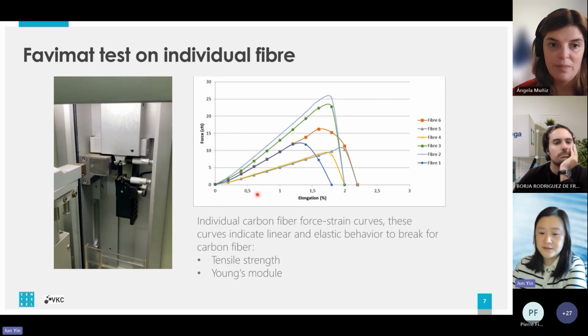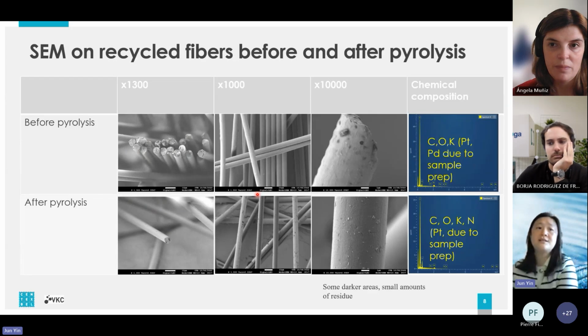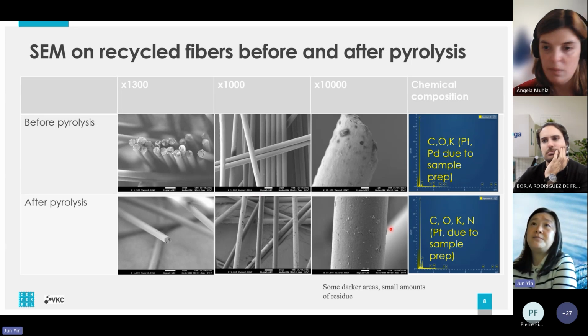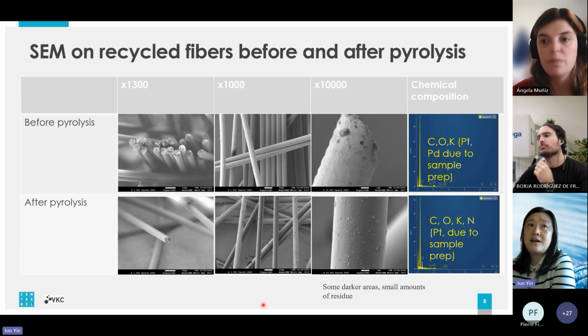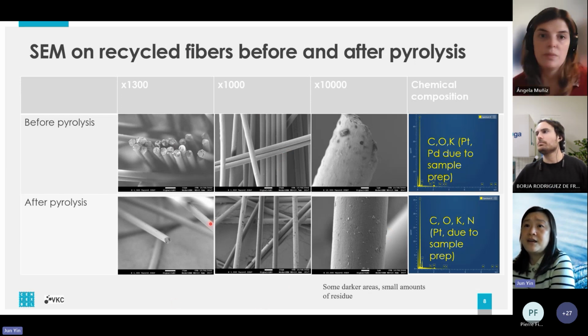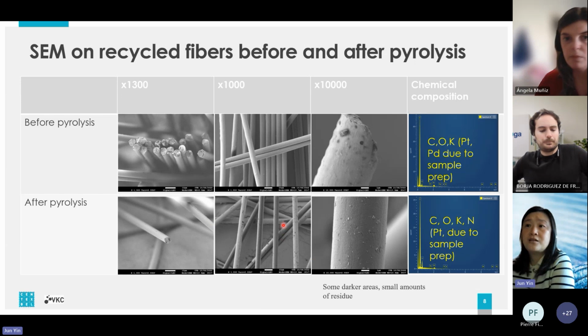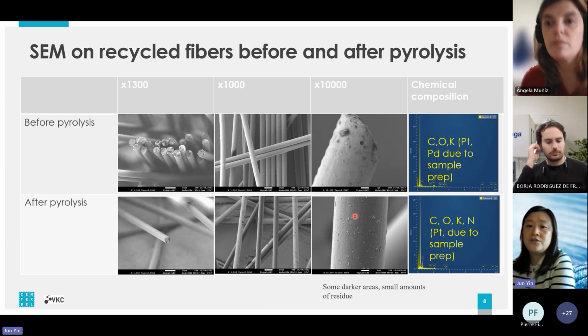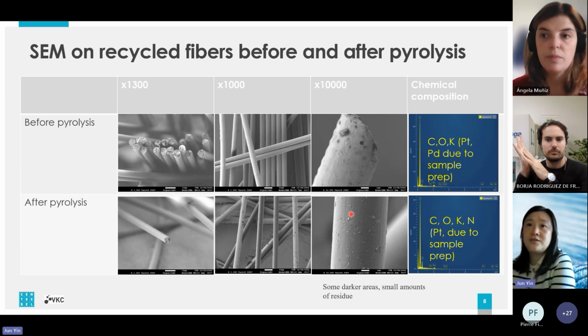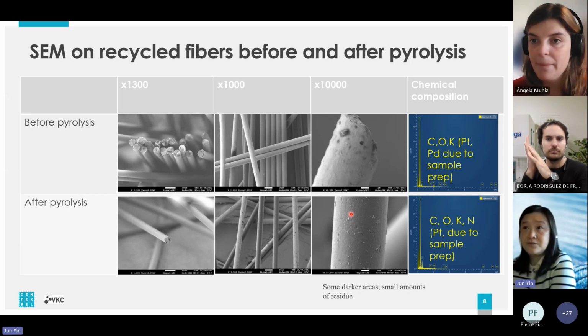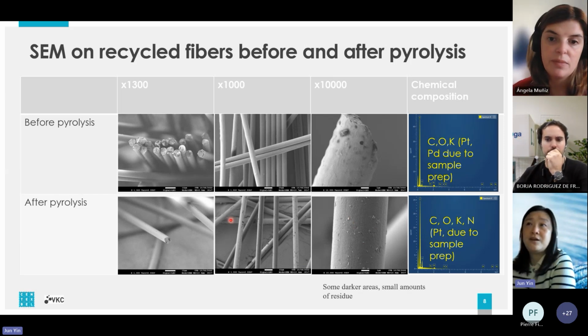Okay, so this is the process of the tensile stress. Then we compare the recycled fibers before and after pyrolysis. Before pyrolysis, we can see the fiber shows a smooth surface, but after pyrolysis, we can see a lot of dark areas and a small amount of residues on the surface. So it's damage on the fiber surface by the process of pyrolysis.